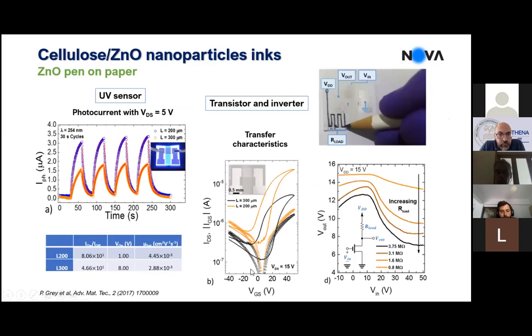And you see that to operate these transistors, you have a large hysteresis window, and you need to use like 40 volts to drive or to modulate the current. That is not that good, the modulation that you get. So I will show some strategies to improve this and to reduce the operation voltage in these transistors by 10 times.